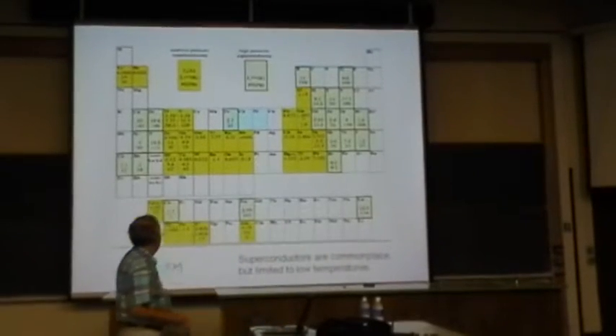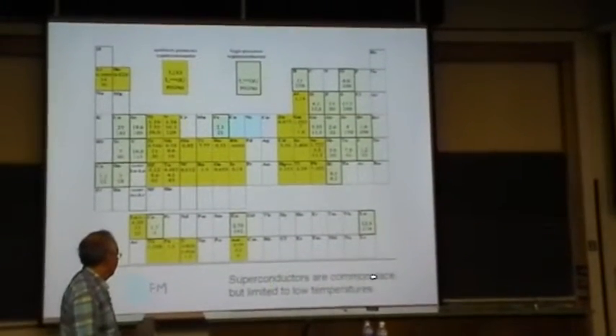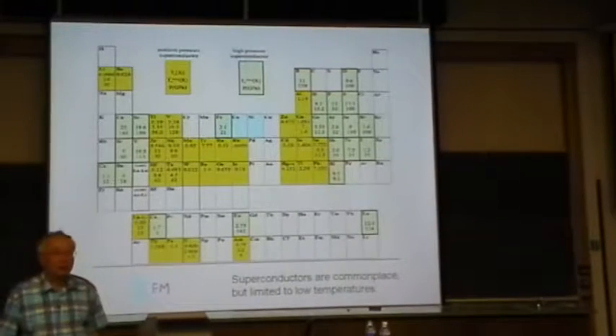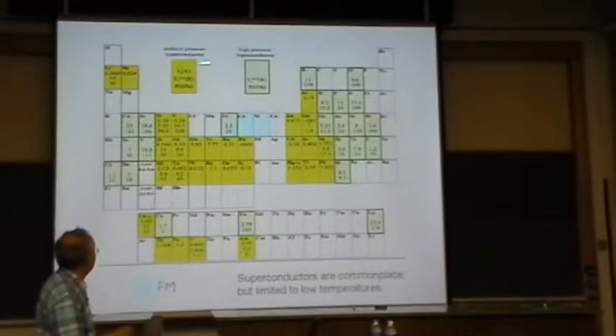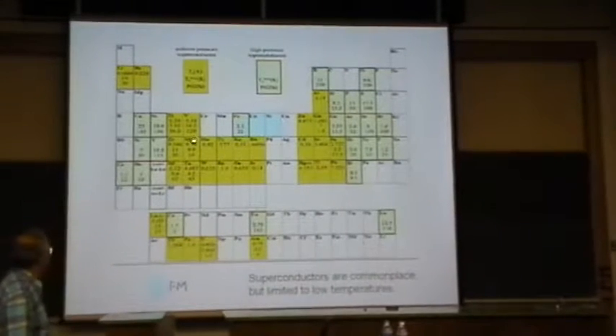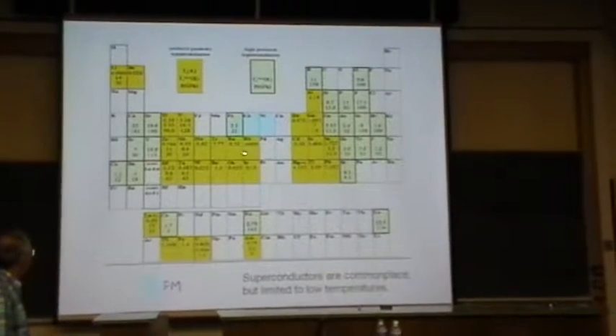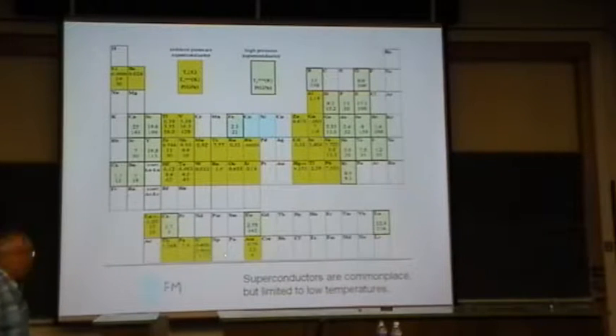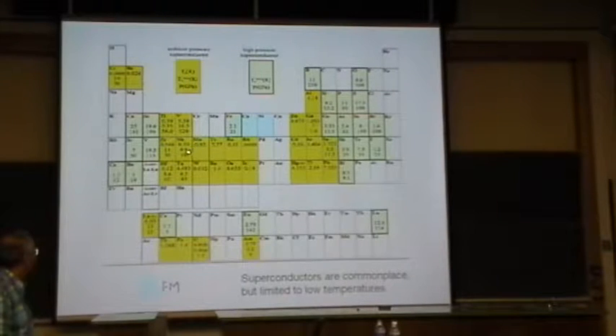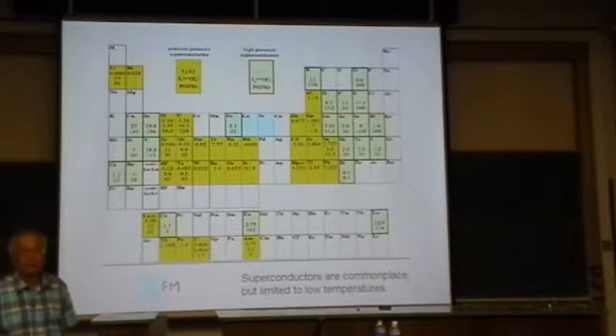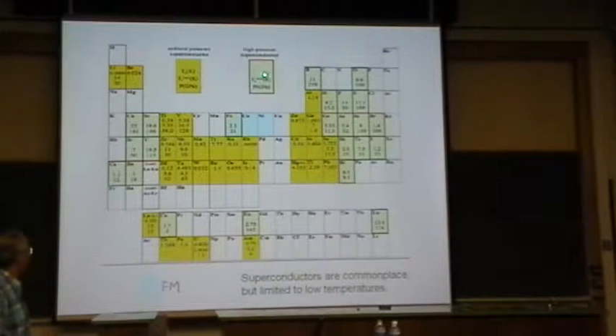Yeah, but even though the temperature is very cold, superconductivity is actually very commonplace. If you look at the periodic table, here we have colored yellow all the elements which actually become superconducting. Okay? And the highest transition temperature is, I think, niobium, which is superconducting at 9.5 Kelvin. The green are the elements which are superconducting under pressure or in thin film form, so they're more esoteric. But you can see that the yellow and green covers pretty much 80% of the periodic table.